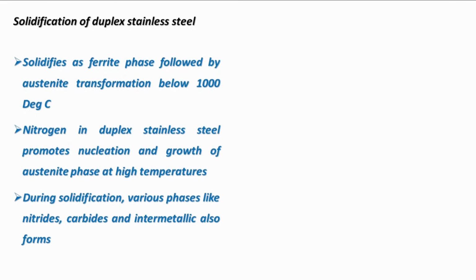The solidification of duplex stainless steel is typical and entirely different from all the other steel materials, including carbon steel, austenitic stainless steel and ferritic stainless steel, because here the solidification starts with the ferrite phase followed by austenite transformation below 1000 degrees Celsius. The advantage of duplex stainless steel is the addition of nitrogen, which promotes the nucleation and growth of the austenite phase in the material at high temperature. During solidification, various phases form, unlike in austenitic and ferritic stainless steels, like nitrides, carbides, and a lot of intermetallics. So this is the solidification pattern of a normal stainless steel based on the chromium and nickel equivalent, as we know.